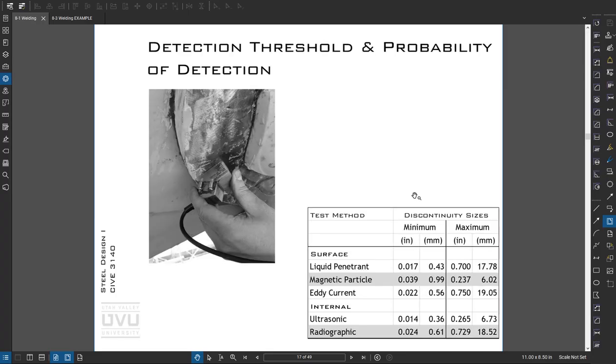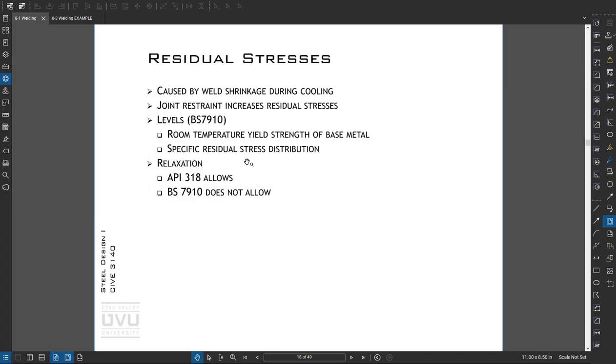Okay, residual stresses as the weld shrinks at different rates, or the base metal is cool and the weld metal is molten. As the weld shrinks, it creates residual stresses. There's a British standard 7910, which will give you the ability to calculate those. API, which is American Petroleum Institute, allows you to relax those stresses. British standard 7910 does not.